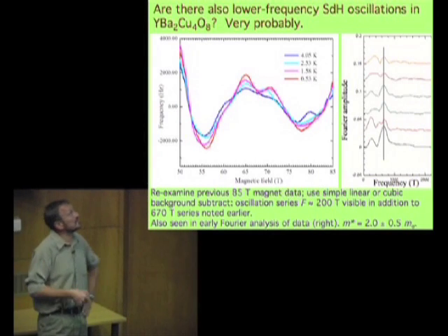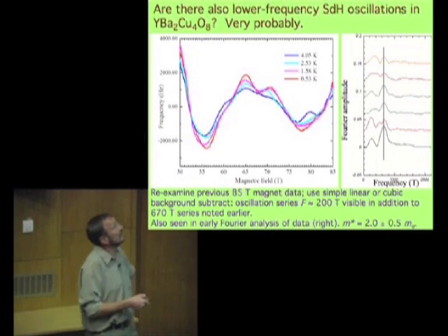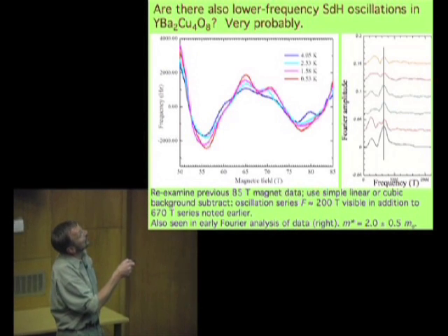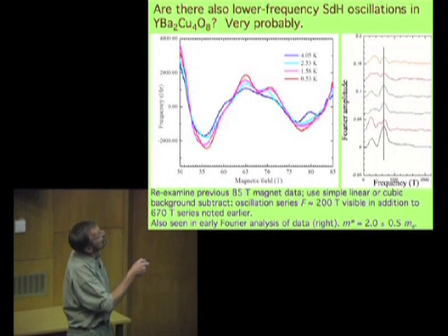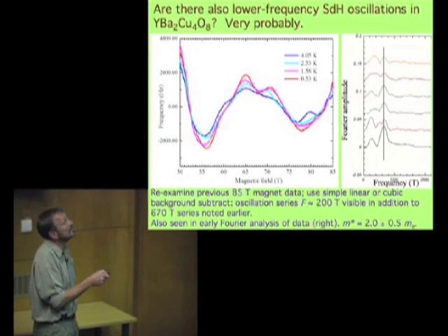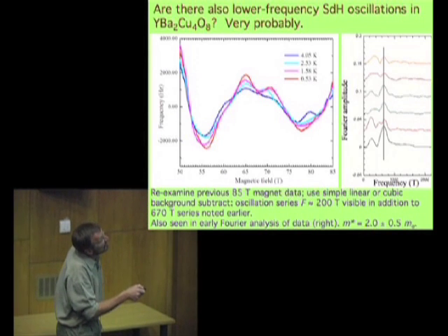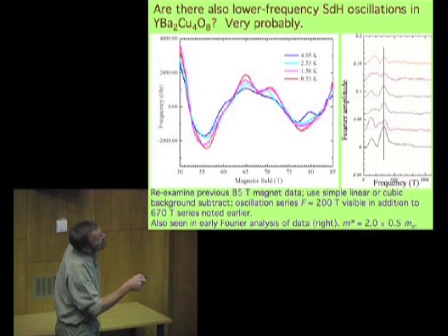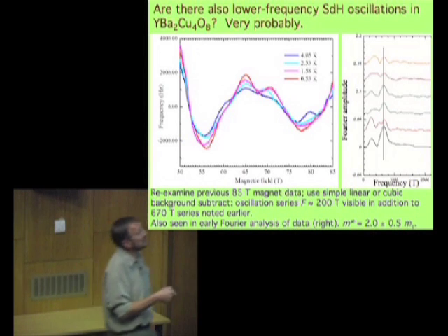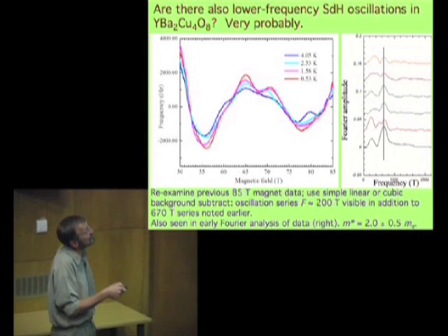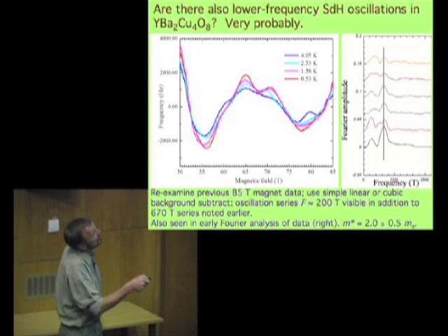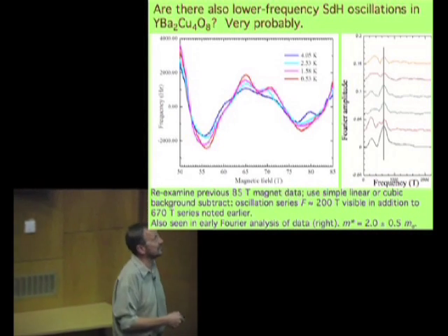Are these lower frequency oscillations present in the other dopings of cuprates? This is again back to the 1248 cuprate. These are now the high frequency oscillations we saw before. You can see them here. If you do a different sort of background subtraction than the one we originally did, you can see that they're superimposed on a lower oscillatory frequency as well.